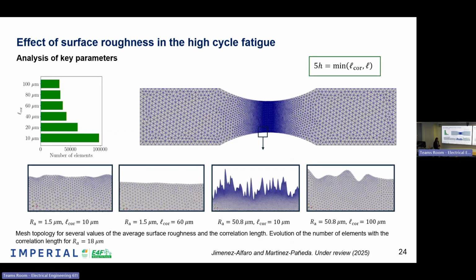Each time I change the parameters, something changes in the computer. This is what I want to show you now. Each time we change it, we change the mesh. Here I have included some different meshes for different cases. I would like to show you just the most critical ones. This is a case for a very low value of the surface roughness and also an average low value of the correlation length. You can see that the specimen is almost flat. It's almost a polished specimen. There's almost no surface roughness.